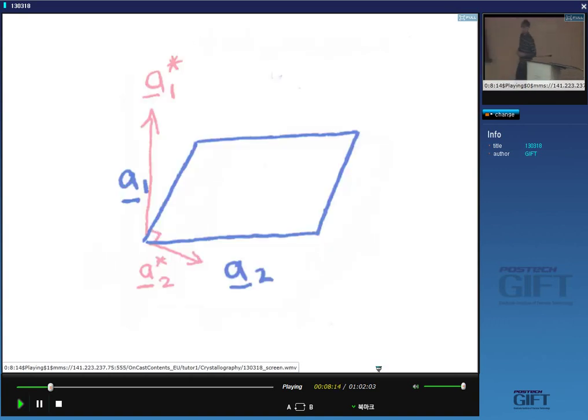Right. Now, in the case of a cubic unit cell, the reciprocal lattice vectors will point in the same directions as the real space unit cell vectors. But that is not generally true. As soon as you go away from an orthogonal cell, that means where the angles are all 90 degrees, the reciprocal lattice vectors will no longer be parallel to the real space vectors. You've already come across this when we were looking at the hexagonal system. You saw that the 100 direction is not parallel to the 100 plane normal. Do you remember that?